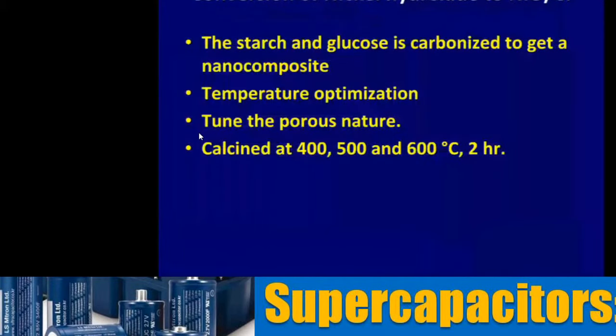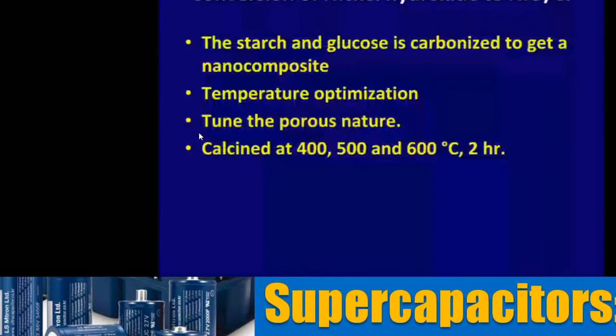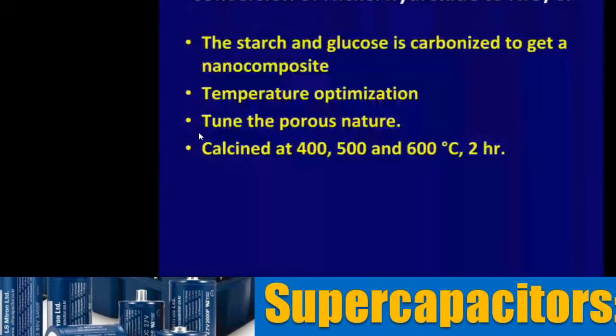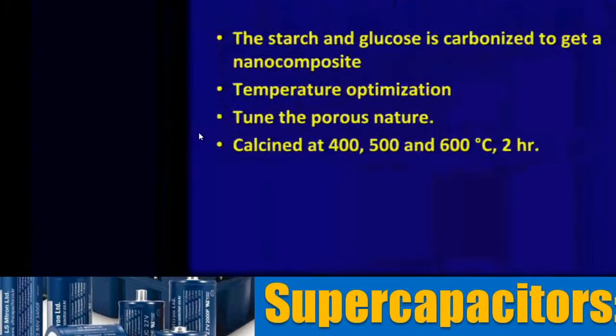Nickel hydroxide as such is not a very good material. We wanted to convert this nickel hydroxide to nickel oxide. In the process, because we have used starch and glucose, we have carbonized the starch and glucose to get a nano composite of nickel oxide and carbon. What we did was we tried to look at different temperatures at which it happens, and also tried to tune the porous nature. Studies were made by heating the material in air at 400, 500, 600 degrees for 2 hours.